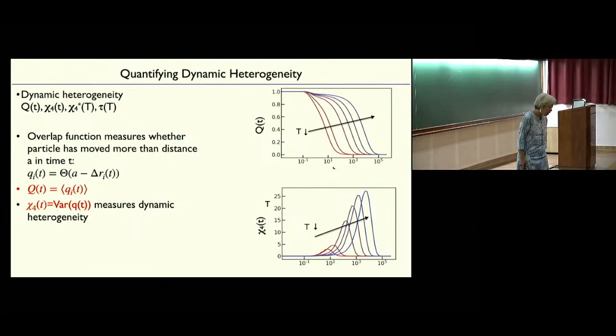It was Jorge Kurchan and Leticia Cugliandolo who showed that in a lot of these systems, at short times, you see the actual temperature. At long times, it crosses over to an effective temperature, which is quite different. And I was talking about that effective temperature.